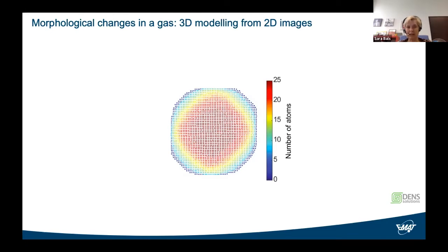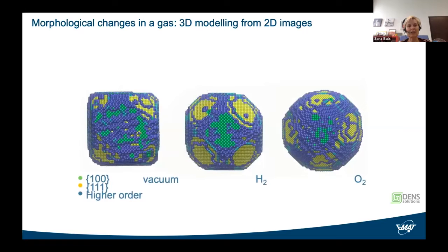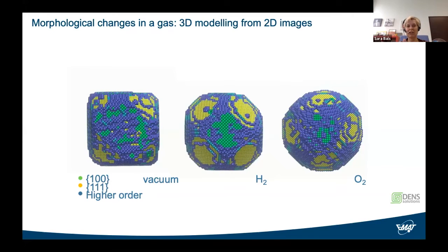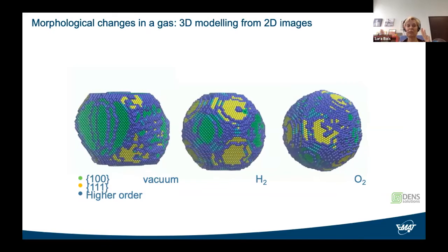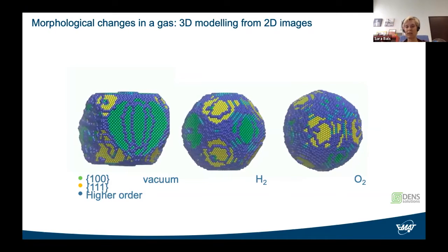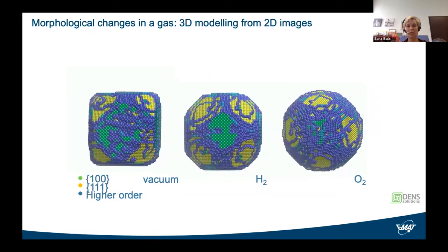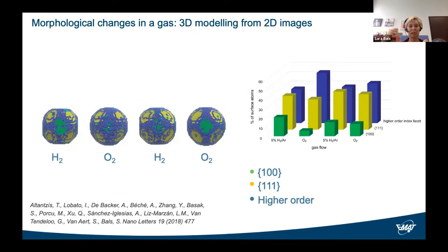Again, we're going to be using this as an input for molecular dynamics simulations, and that allows us to compare the structure of these particles in vacuum with the structure of these particles in hydrogen and oxygen. And we went back and forth between hydrogen and oxygen, and we could also see a transition between a faceted nanoparticle and a rounded nanoparticle. We can again quantify this, and we could see that if we perform some sort of cycling investigation, at a given point, the higher order index facets start decreasing. And that obviously is important if later on people would want to use these particles during catalysis.